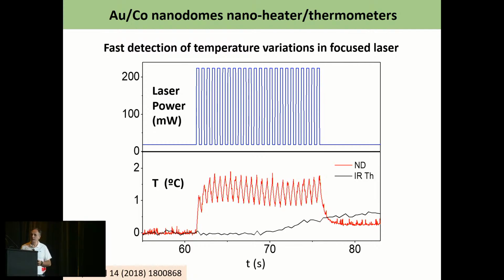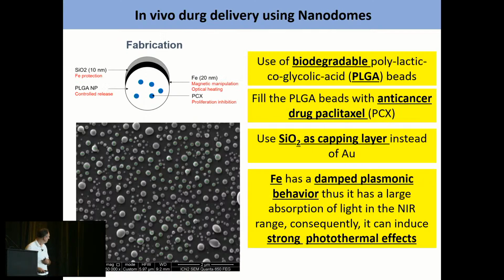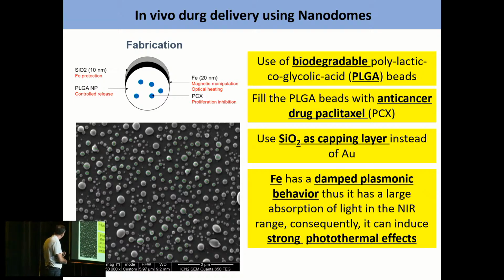So we were encouraged by all these results, so we decided to try in vivo. So I'll go to the other side for a while. So now, to do the in vivo experiments, we changed our structure slightly. First, instead of using polystyrene beads, we changed to biodegradable PLGA beads, which we filled with an anti-cancer drug, PTX. And now, instead of using gold, we use silicon oxide as a capping layer.